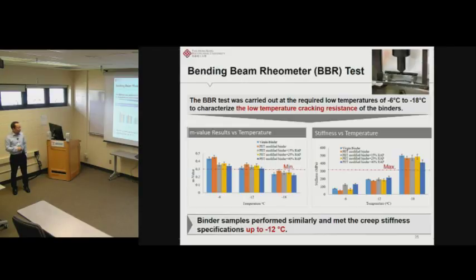So our virgin binder actually can meet the requirements at minus 12 degrees C. And after we add the PET additive and even the RAP binder, we can still meet this low temperature grade requirement. In terms of low temperature grade, we can see the PET can slightly improve it, but the difference is not that significant.